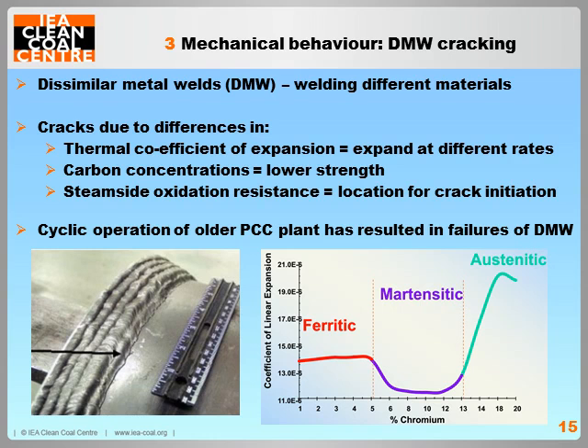They expand at different rates, and also localized oxidation forms, which is an ideal place for crack initiation. So, cyclic operation of older plants results in failure of dissimilar metal welds. New components have reduced the risk of dissimilar metal weld cracks through thermal coefficient matching and component design to minimize the stress on the weld.